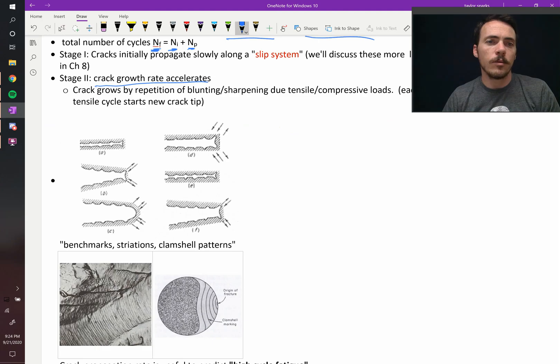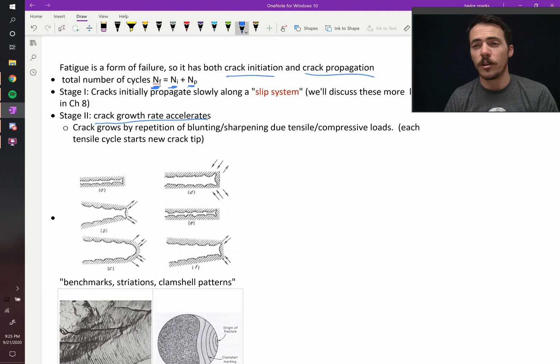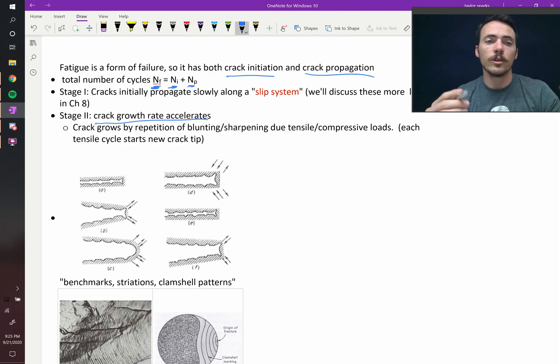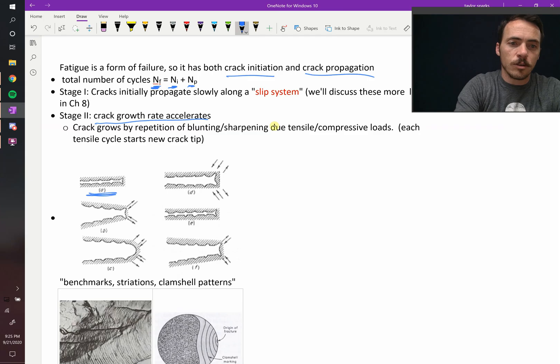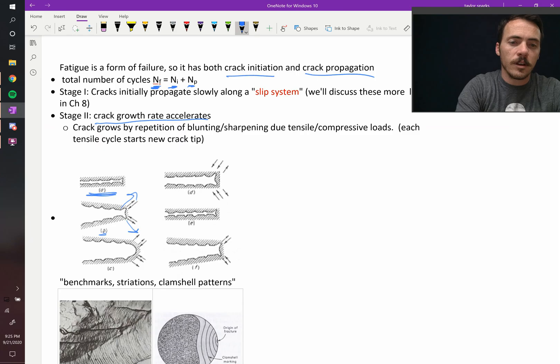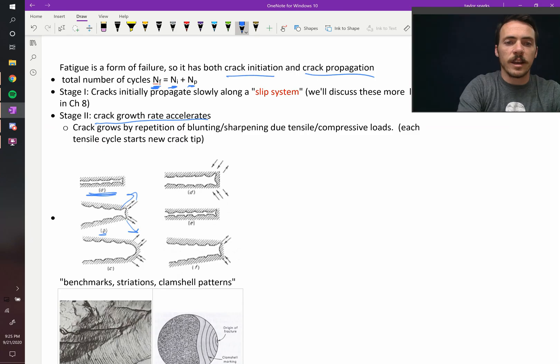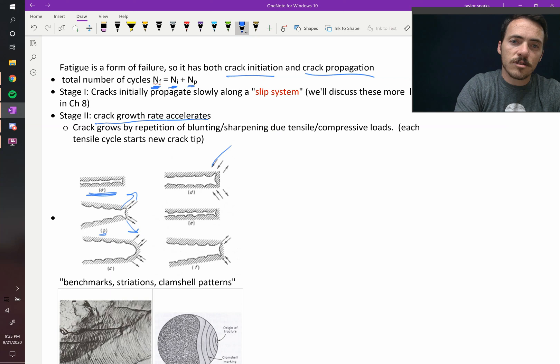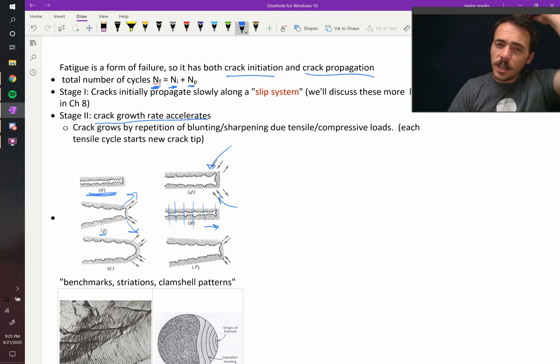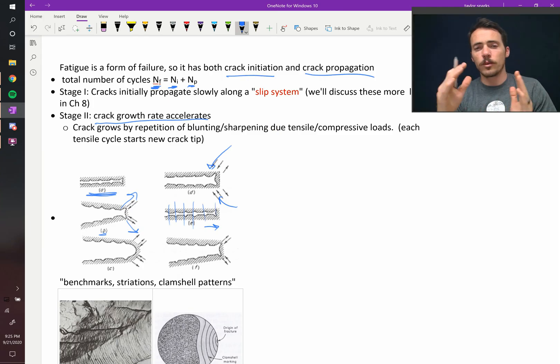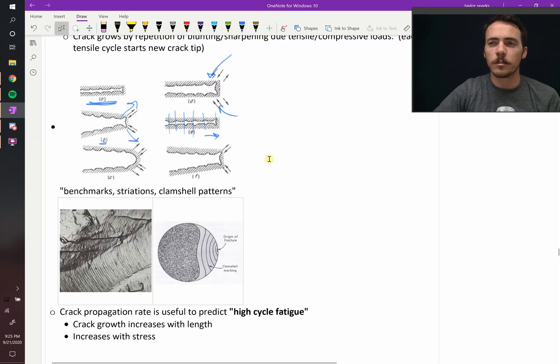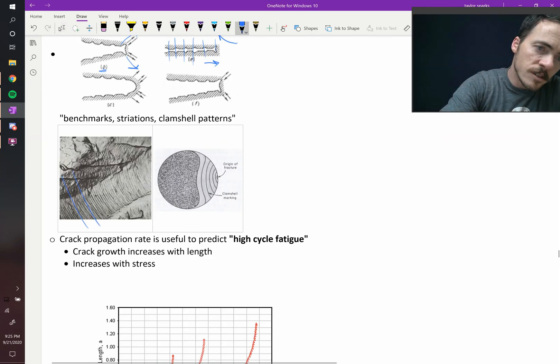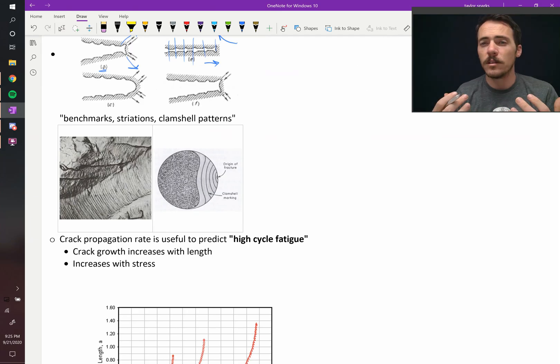And as it grows over time, especially if you have a scenario where it's going from tension to compression, what you'll see is this. So here's our crack. As you start to pull on it, you're expanding it. So the crack is getting larger. It's being torn a little bit that way. And then it stops being loaded. So it's static. And then you compress it again. So these get squeezed back down. And now you've incrementally moved your crack over. So these lines represent each cycle. Each cycle, it pushes a little bit forward and then it squishes again, pushes a little bit forward and squishes. So we call these benchmarks. Sometimes they're called striations or clamshell patterns. You can see these stripes in that material. Each one of those represents a cycle of fatigue.